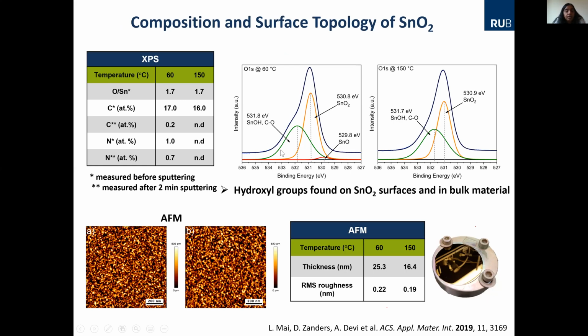So you sputter the first couple of monolayers, or first nanometer layers, and then you look into the bulk of the film. And here you see, at 60 degrees or 150 degrees centigrade, that the films contain species, not only tin oxide, but also some hydroxide species. It is reduced at high temperature, but still there's some contribution. This is a very good sign to show that it's not only SnO species, but also SnOH species inside the film. That can also be one of the reasons that we may not have a perfect stoichiometry.